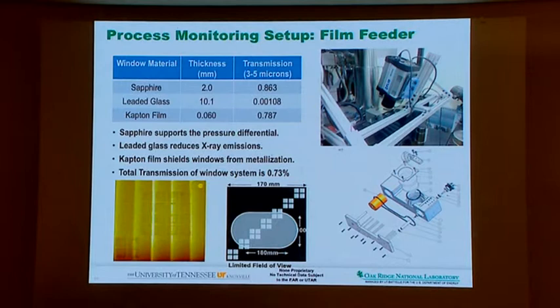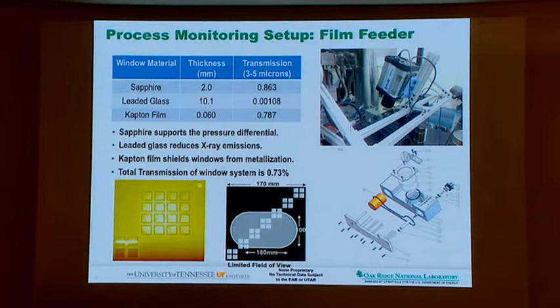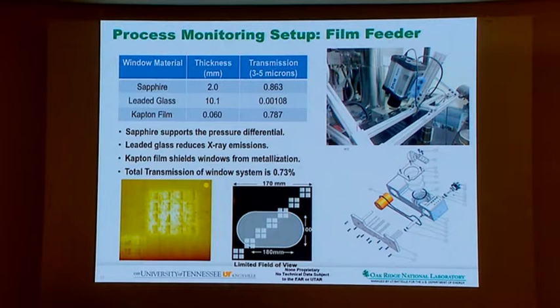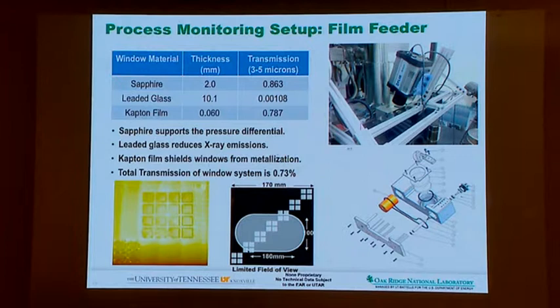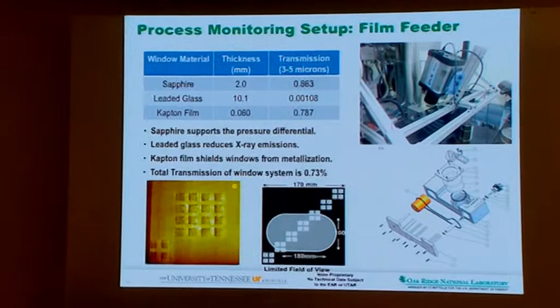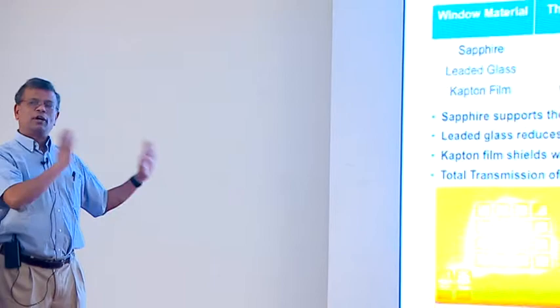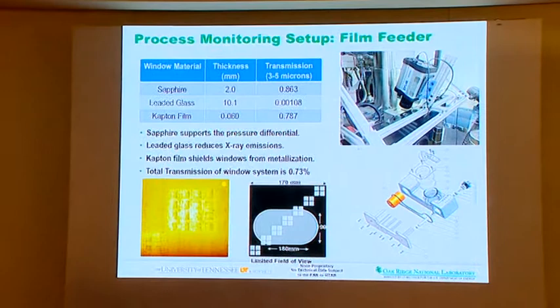This is not new, because welders have known this for a long time. They put infrared cameras, and that's what you're seeing in that video, where a high-speed infrared camera looks at the layer as the electron beam melts it. If you have each and every pixel there, you can see the heating and cooling in that pixel as a function of time. To do that, we have to jerry-rig the additive manufacturing machine, put a hole there, and put in an infrared camera, which is actually a FLIR camera, which gives you the temperature distribution. A lot of innovation went into it. If you are interested in that contraption, we can talk about it in the Q&A.